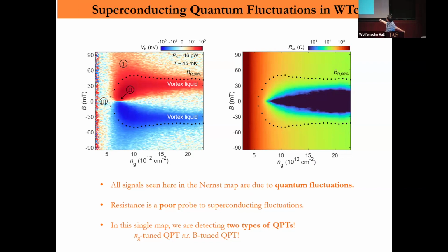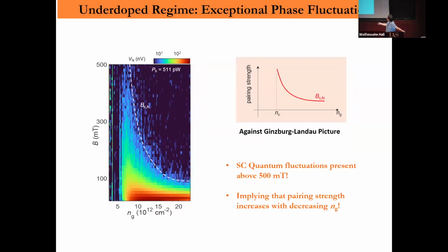What's absent in the resistance measurement is something like here, something like this, right? Which is highlighted in this map, where now the resistance, the magnetic field applied up to 500 millitesla, it's very big. So you see that's a boundary we call BCN, the white curve, which rapidly goes up when you go to lower density, approaching the critical point.